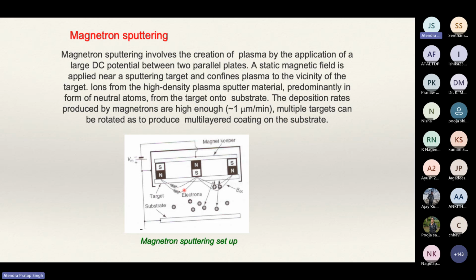That's the idea, because the more sputtering ions over the target, the more target atoms will get knocked out by these ions. This is one of the reasons why people use magnetron sputtering: the deposition rate in magnetron sputtering is pretty high. It goes to something like 1 micrometer per minute, whereas in normal deposition, either e-beam deposition or thermal deposition, we talk about something like a few angstroms per minute.